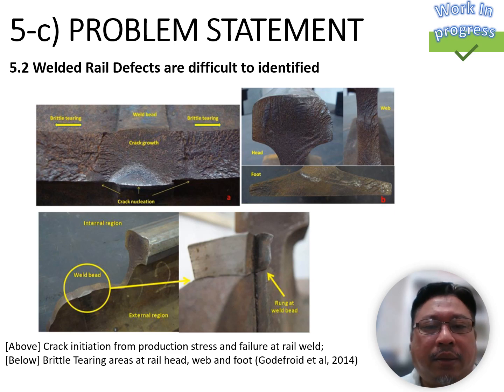On the second problem statement, welded rail defects are difficult to identify. Rail has 3 distinctive parts: the head, the web, and the foot. For typical UIC modern rail, the head thickness is around 50 mm, the web thickness is about 16 mm, and the foot is 144 mm wide. The ultrasonic detection transducer requires 3 different angles, 70 degrees, 40 degrees, and 0 degree, to penetrate the whole rail, and requires a skilled worker to interpret the results. And the process is very slow and time consuming. So these are the defects that occurred at the weld joint, weld bed, and most of these need to be analyzed using the ultrasonic inspection machine.